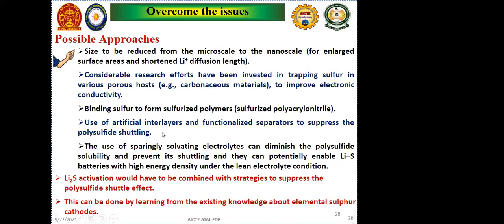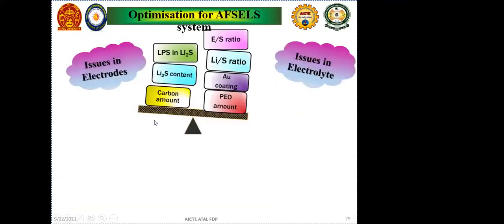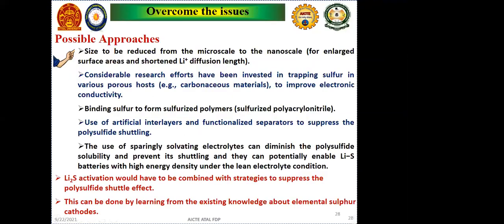So here, apart from that, we can also make artificial interlayers in the electrolytes. Like when you use the separator, we can go for coating of the separator with some polymer, so that the formation of dendrites will be reduced, or the SEI layer will not be destroyed if we coat some other layer on that surface, or we generate some artificial SEI. So that will also be helpful.